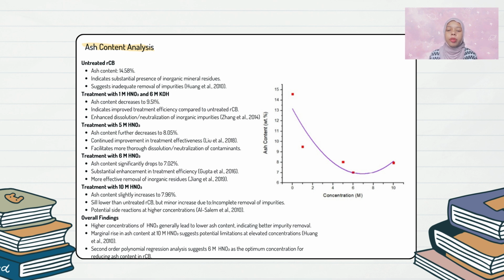Secondly, treatment with HNO3. As the concentration of nitric acid increased, the ash content decreased. Specifically, we found that a 6 molar concentration of HNO3 was the most effective in reducing ash content, indicating optimal impurity removal at this concentration.